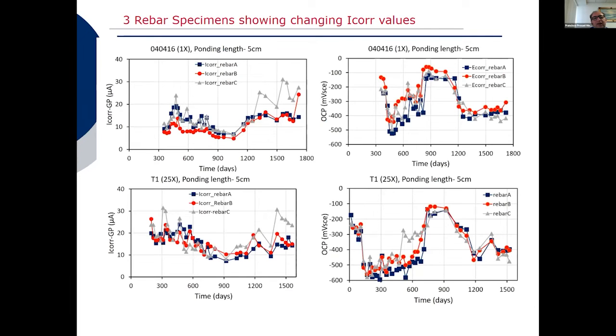In other samples, we have a slightly different behavior. In this particular specimen, you can see that the corrosion current increased, went down, increased again, went down a second time, a third time, then had a decay and reached a minimum, and more recently we have observed that in some of them, again, they start increasing. So these oscillations towards larger values might be indicators that additional sites are becoming active, or that the corrosion area has increased, or likely a combination of the two.